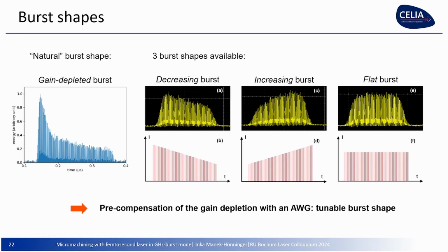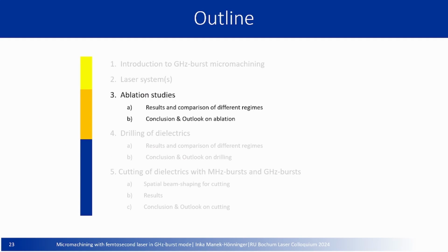And this is why I showed you the 2 laser systems, and then later on we were working on formed bursts. We were mainly forming a flat burst, but we made also some studies with a decreasing burst. So these are the ideal bursts, and these are the real life screenshots from your oscilloscope, a decreasing burst or an increasing burst. This is the arbitrary wave generator that allows for it. There was an AOM to pulse pick the wished length of pulses, of course, and there was an EOM as well, just to have steeper flanks, because the AOM is longer in time range. Okay, this is for the laser system.